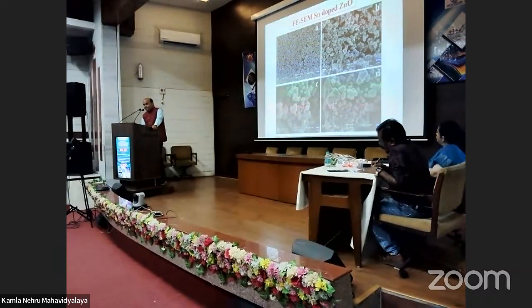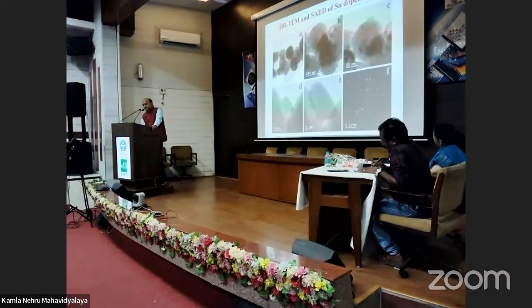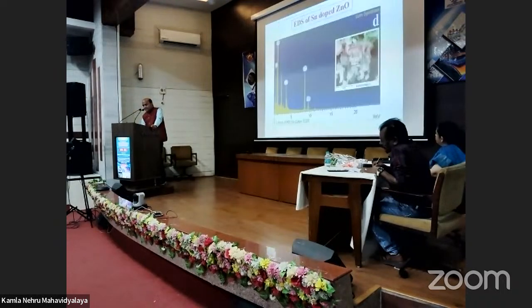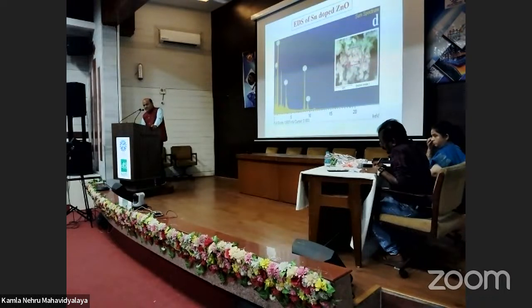This is the FESEM, where a uniform and very scattered form of tin doped zinc oxide is observed. This is the high resolution TEM and SAED pattern for this particular material, polycrystalline. This is the elemental composition study, showing the presence of Sn, zinc, and oxygen.